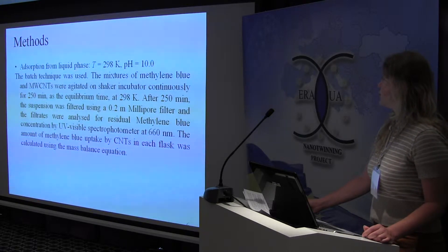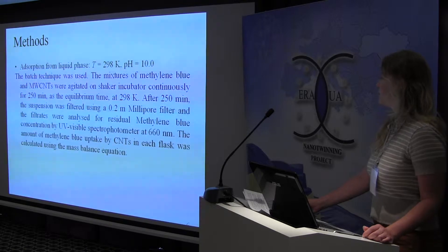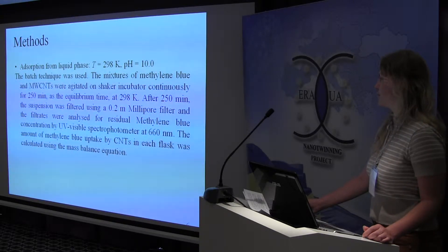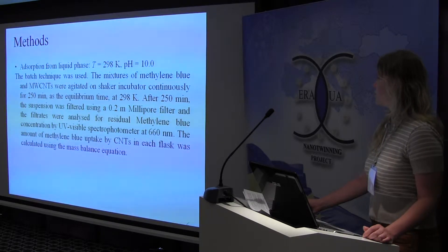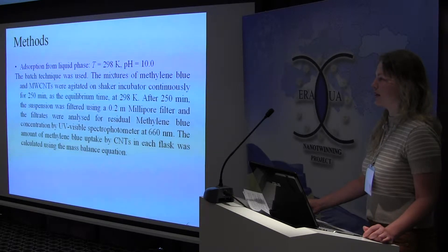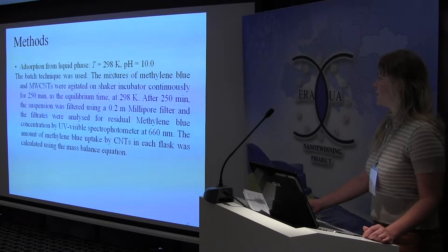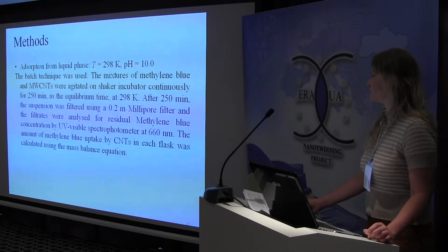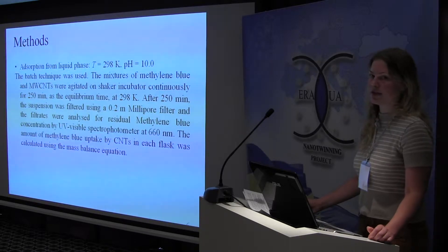In our work we used adsorption from the liquid phase using the batch technique. A mixture of methylene blue and multi-walled carbon nanotubes was agitated for 2.5 hours equilibrium time at 298 K. After that time the suspension was filtered and the filtrate was analyzed for residual methylene blue concentration. The amount of methylene blue uptake in each flask was calculated using the mass balance equation.